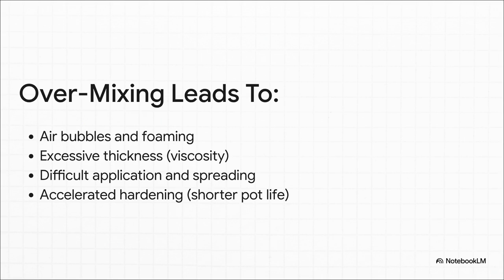See, overmixing creates its own disaster. You're essentially whipping air into the mix, which creates these tiny bubbles. Later on, those bubbles become weak points, pinholes in your final waterproof barrier. The material also gets way too thick to apply smoothly, and it starts hardening right there in the bucket. That dramatically cuts down your working time, your pot life.